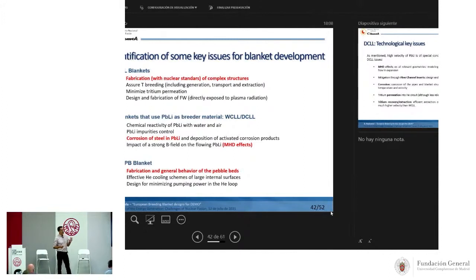Some issues related to blankets that use the liquid metal. The first one is to avoid the chemical reactivity of the liquid metal with water and with air. Next, we have to control the impurities in the liquid metal. Also, another important issue is the corrosion of the structures due to the interaction with the lithium, and the MHD effects. And in particular, for the other driver blanket, which is the HCPB, we have some issues such as the fabrication and the general behavior of the pebble beds.